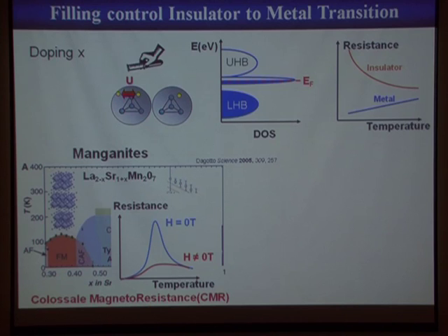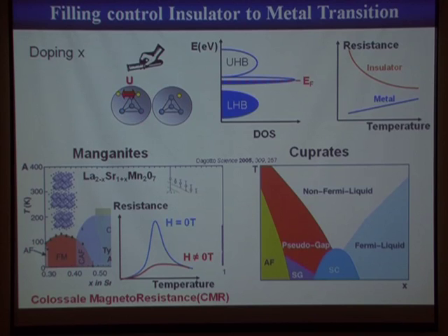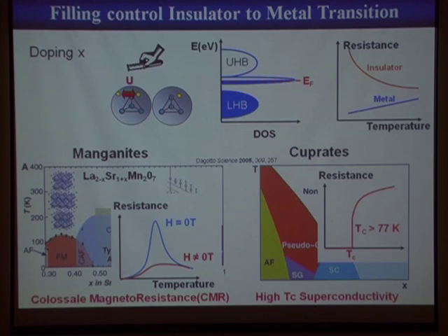The other famous example is the cuprate family. When you dope a Mott insulator cuprate, you reveal a general phase diagram and enter the high-Tc superconducting phase. I show these examples because when you have a new family of Mott insulators, you should try to induce either filling-control or bandwidth-control insulator-to-metal transitions to reveal very interesting properties near the transition.